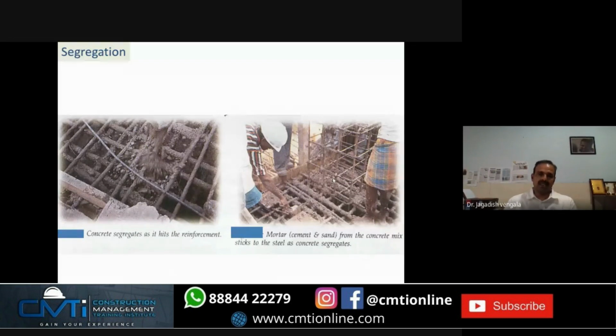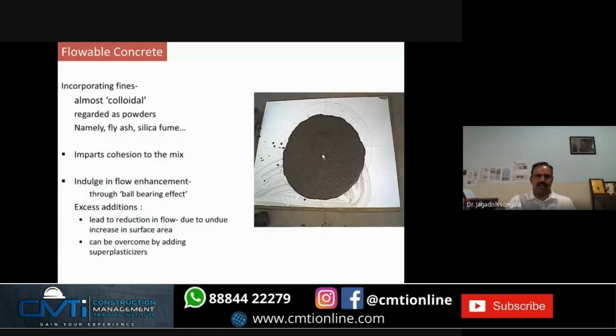You cannot place the concrete from more than a particular height. We call it, they say 1.5 meters, free fall. You cannot throw concrete or place the concrete beyond 1.5 meters height. What happens, particularly with congested reinforcement, when you are placing at a height, the concrete hits the reinforcement and it segregates. Mortar sticks to the reinforcement and coarse aggregate goes down if your mix is a segregated or bleeded mix, if your mix is not good. So these are the problems that happen, particularly for complex reinforcement situations.